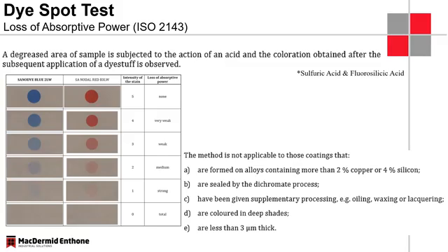So this is the dye spot test, and a lot of companies use this test to determine the sealing quality of the anodized part. What we use here is an acidic solution, normally sulfuric acid and fluorosilicic acid. We drip that onto the surface of the sealed and finished component, and we let it react on the surface. And depending on the quality of the sealed surface, it will open up these pores more or less. For a good quality sealed component, it will open up the surface less. For a poorly sealed surface, it will actually open up these pores significantly more.